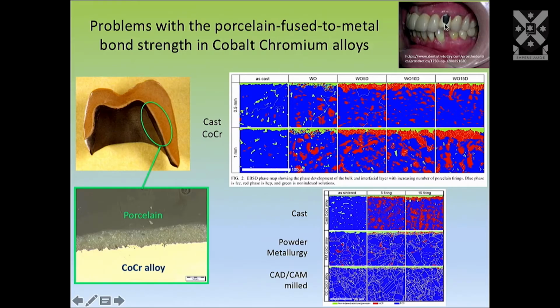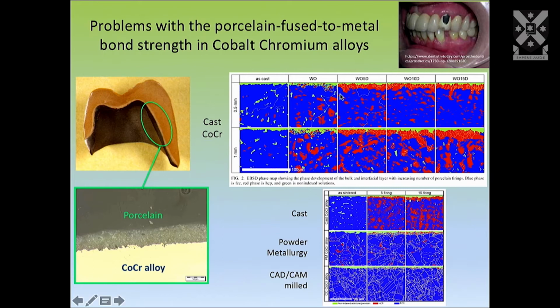Coming to the cobalt chrome side, what we were seeing was a failure at the porcelain to metal interface where porcelain was breaking away. And what we found was that when we used electron backscatter diffraction to look at what was going on at the surfaces, what you see here is a 0.5 of a millimeter and a 1 millimeter thickness. So this area here would be that thickness. And we then placed porcelain on top of it. The little green area you see at the top is the porcelain, and that represents this area here. So there's your porcelain on top of the metal.